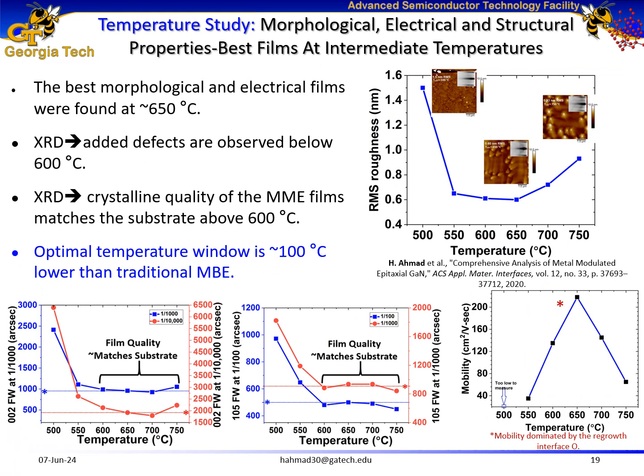Then I studied the effect of the first growth parameter, which is substrate temperature, in the range of 500 to 750 degrees C, and I found the best morphological and electrical quality films at a substrate temperature of 650 degrees C. From X-ray measurements, we found that our regrown films match the quality of the template above 600 degrees C. However, below 600 degrees C, we found added defects. This temperature window is approximately 100 degrees C below the traditional MBE growth temperatures, making MME more suitable for commercial use.